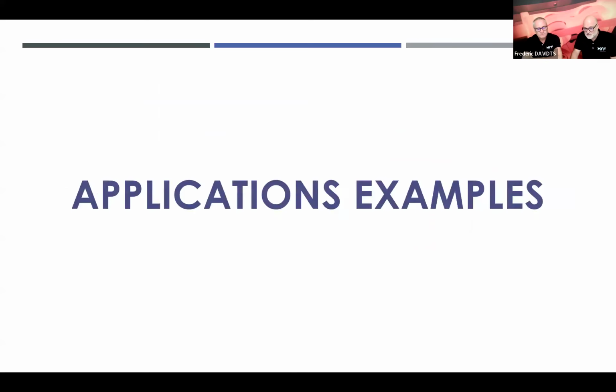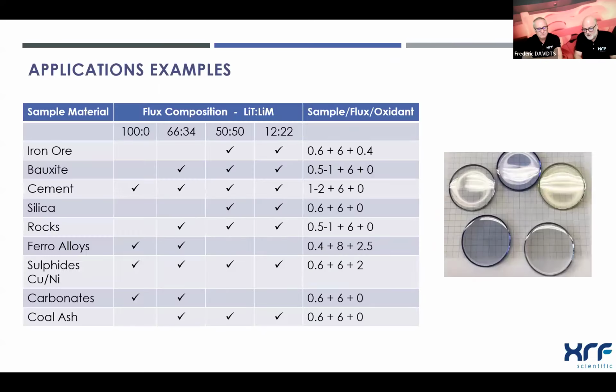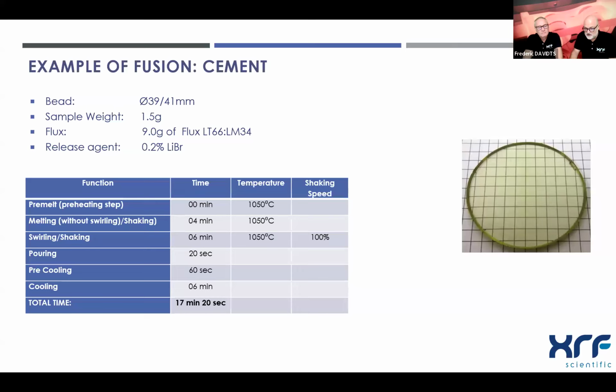Yeah. Now some applications. For different types of materials like spinels, there are fluxes that are more appropriate, and of course according to the acidic or basic character, you will prefer, for example, for silica, a flux with more lithium metaborate, and here are some examples of dilution that are good to use, and we can of course help with that. Here I take the example of the production of cement, 40 millimeter bead. We put 1.5 grams of sample with 9 grams of flux 66:34 and 0.2% lithium bromide, and in 17 minutes we have the beads cold to cold, meaning that we put the crucibles in cold with the mixture, and then we can collect the beads and the crucibles cold.